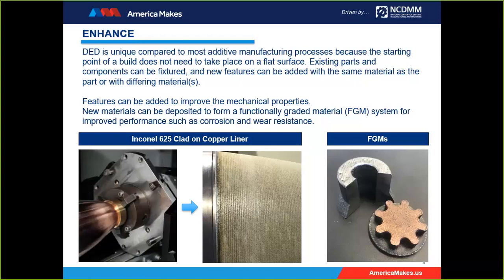The images below show an Inconel 625 clad on top of a copper-based liner on the left image. The image on the right is an example that we produce at FormAlloy of functionally graded material systems. The part in front is an Inconel 625 and transitions into a copper piece on top. Whereas the piece in the back of the image is a transition from an Inconel 718 into an Inconel 625. And finally, a cobalt-based alloy called Stellite 6, which is a commonly used alloy in laser cladding for corrosion resistance.